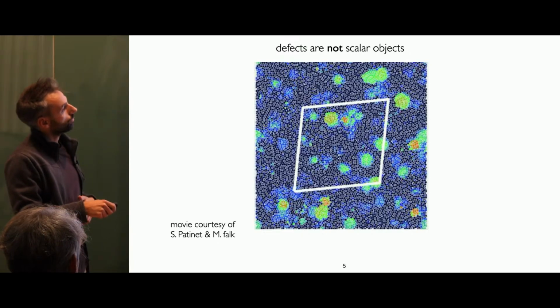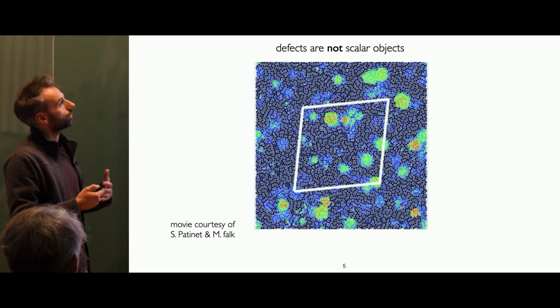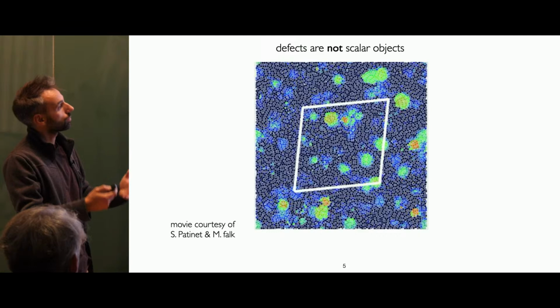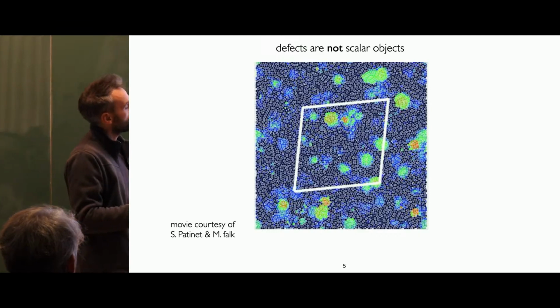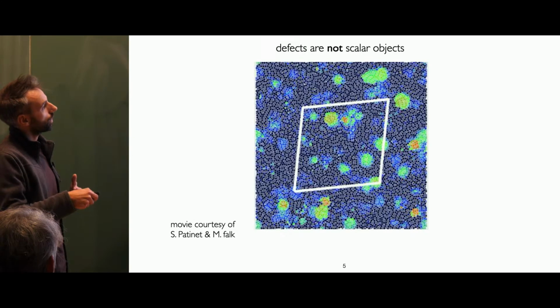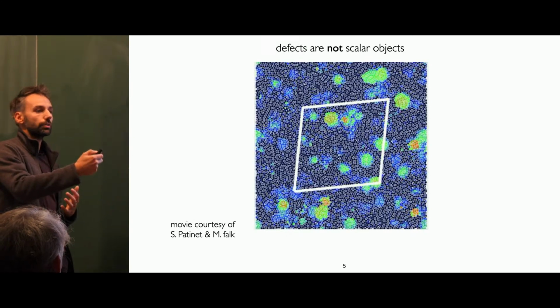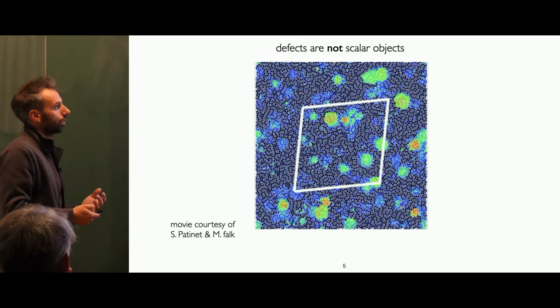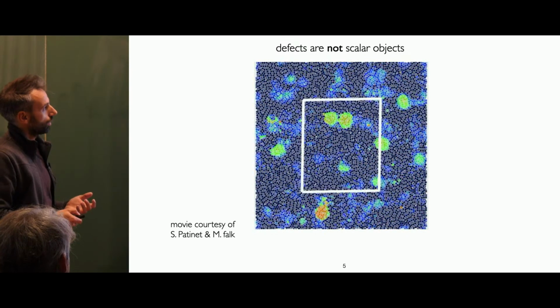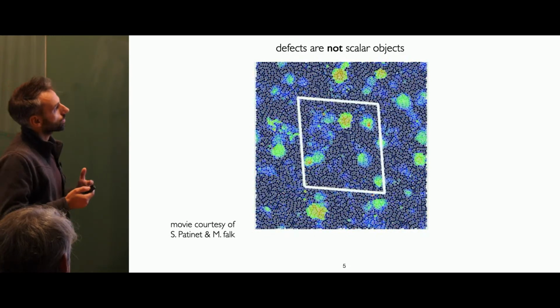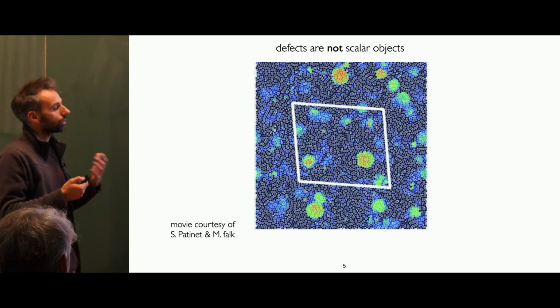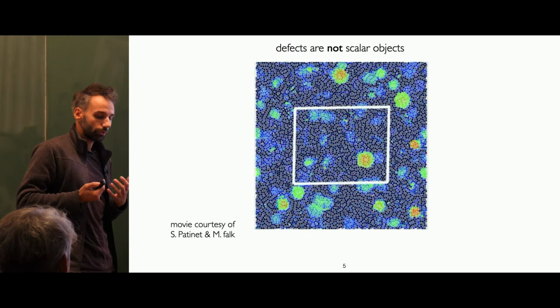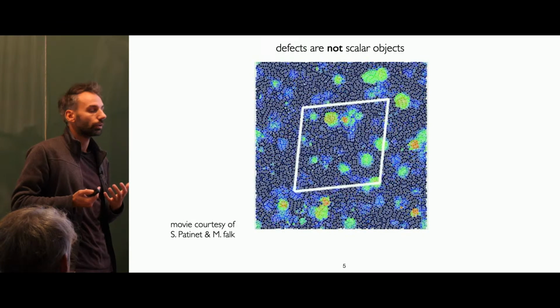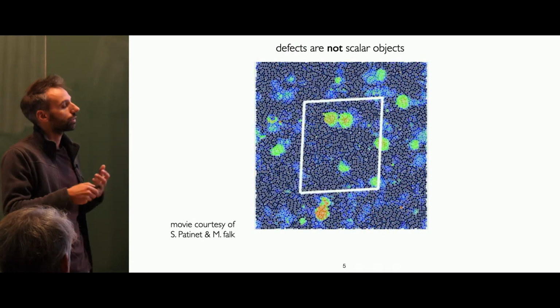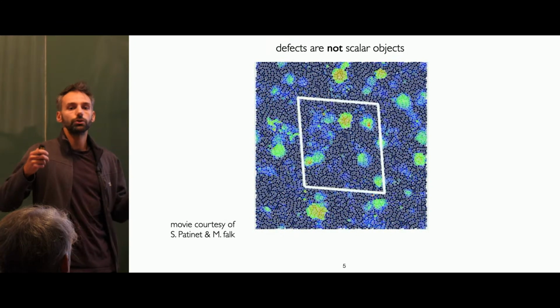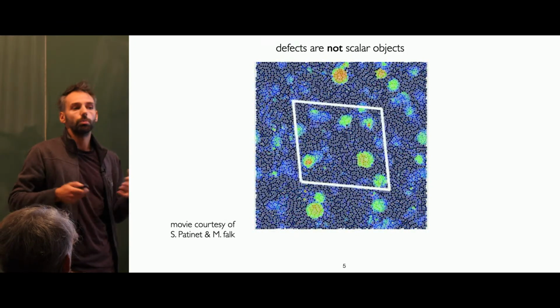That's maybe familiar also for viscous liquids, where you have locally unfavored or locally favored structure that will promote relaxation. But in the case of mechanics, here I'm showing you the local yield stress in one particular deformation, but I could do this in an arbitrary deformation. And when you start to do this, what you realize is that in the context of predicting plasticity you don't only want a scalar quantity, but really a tensorial indicator, because some defect that might be relevant under simple shear might not be relevant for pure shear, for example.